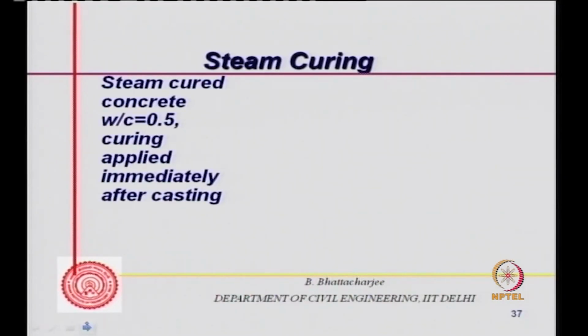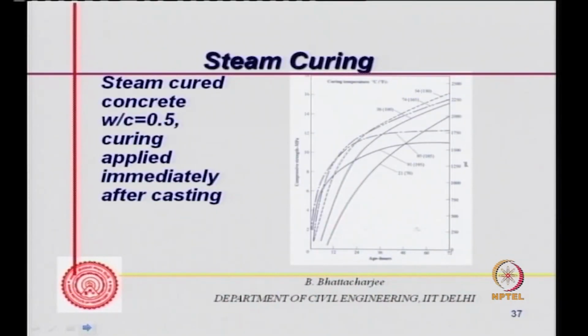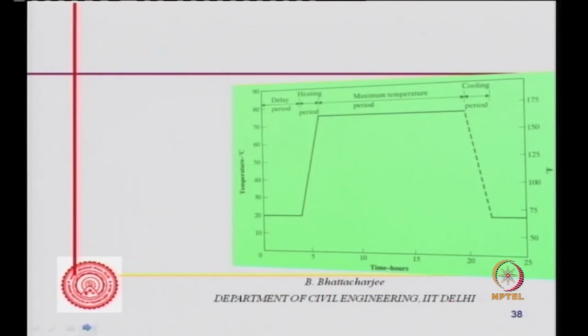So we'll just look at steam curing. If steam is applied immediately after casting, strength gain is poor. But if you maintain it at 74 degrees centigrade, you are somewhere here in this curve; 54 is somewhere there; 31 is somewhere there. At 91, you don't get the strength gain. Compressive strength at different ages is given in hours, 72 hours, 3 days strength. So around 74 degrees centigrade, you get good strength in 3 days. Very high temperature doesn't give you very high strength. Generally, steam at atmospheric pressure will be about 75-80 degrees centigrade.